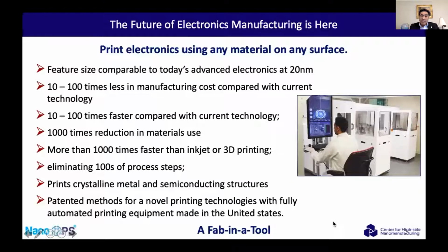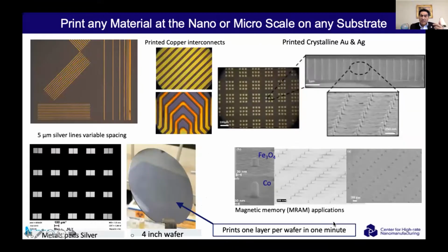And so some of the features: you can print any material on any surface, any material that you can suspend in a liquid. It's all solution-based. Feature size has been demonstrated down to about 20 nanometers. It is 10 to 100 times faster than current technology. It's about 1,000 times reduction in material use. It's all additive. It's about 1,000 times faster than inkjet or 3D printing. And you can print crystalline metal or semiconducting structures. And so the whole thing is one tool that you can see right here. So how does it work?